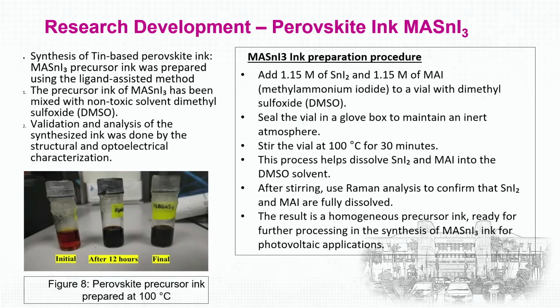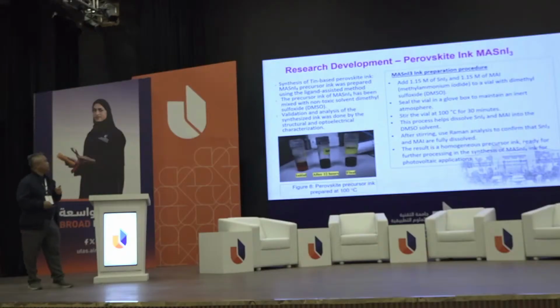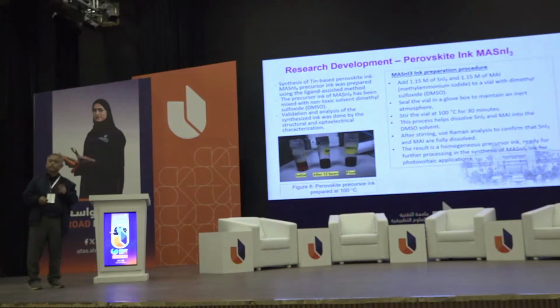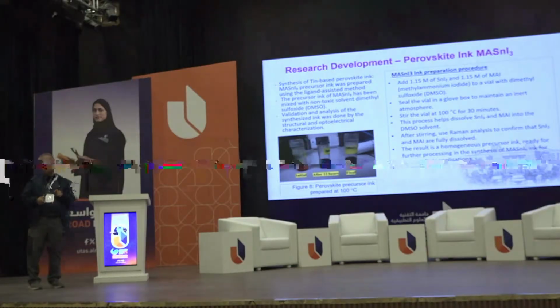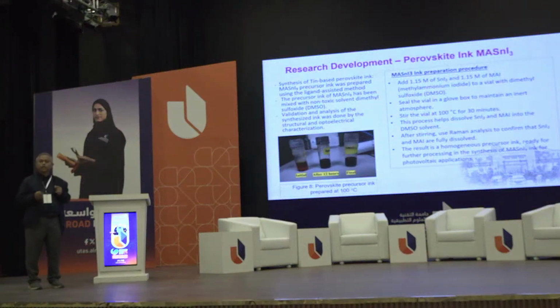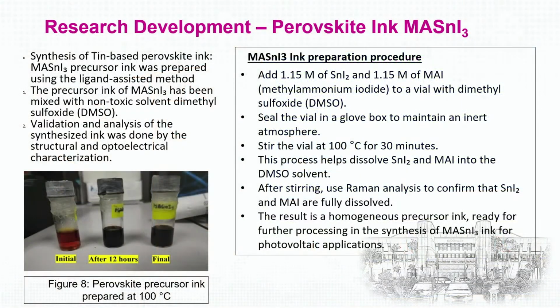So thirdly, we do research on methylammonium tin iodide using a different method, a tin-based material. So this will be a different material, but the problem of this material is stability, which is not stable when it is exposed to the air. So this will be quite challenging for us, but we are progressing to find the best solution in order to solve this issue.